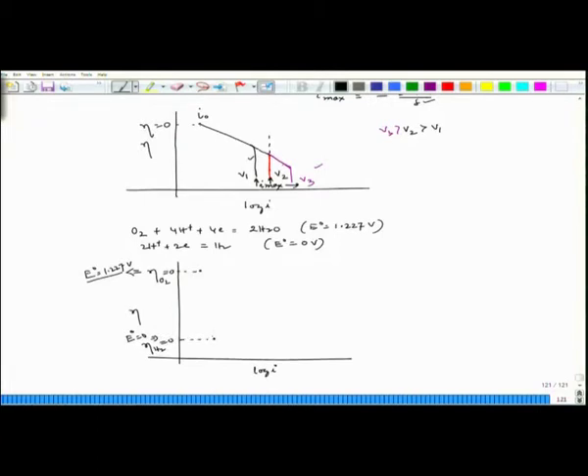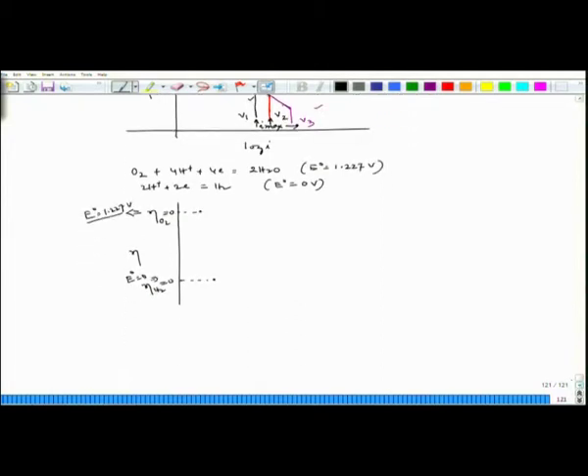at this point. Let us say I shift this particular plot a little down, so that we will be able to see the variation. This is log I, this is I0 for the hydrogen reaction, this is I0 for the oxygen reaction. Now, oxygen will have its own cathodic activation polarization. Let us say this is my activation polarization of oxygen reduction. Let us say this is my I max for oxygen reduction. That means it cannot go beyond this point, it can come up to this point, and then it will take this particular path. So, this path is out as per our understanding.